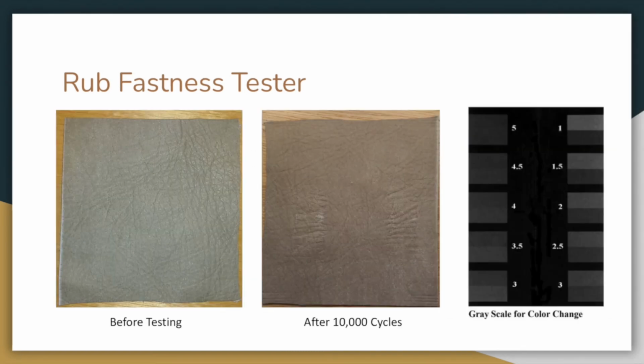So if we move to the next slide, this is an example of a test done on a scrap piece of new leather, tested to 10,000 cycles. There's a noticeable but not huge color change, although the leather has bunched up where the felt was interacting with it. On the right is the actual gray scale, and you can see that as the values decrease, the difference between the two grays increases. This particular test would score at around 3.5 or 4 to illustrate how the results are interpreted.